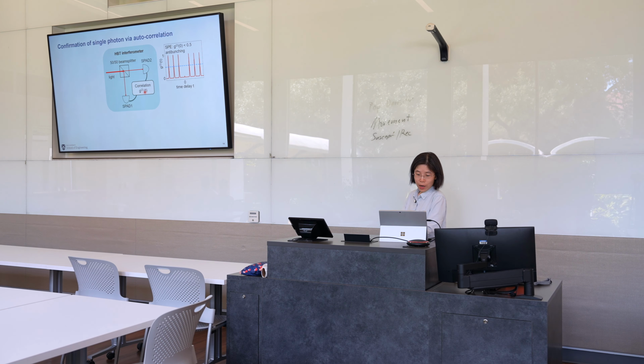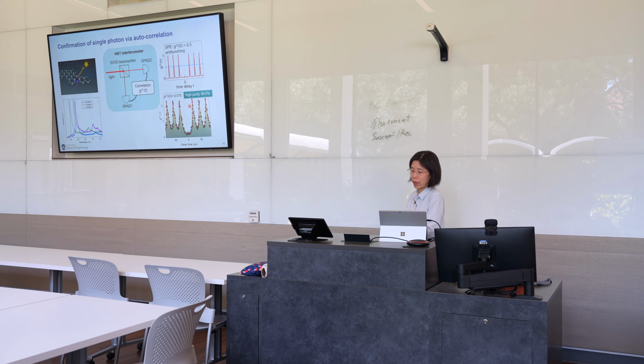Now, if we look at the carbon defects in our boron nitride, we send the emitted light to the HBT interferometer, and this is our experimental result. You can see g2 at zero time delay is very, very small. It is as small as 0.015. And this actually translates into a high single photon purity, 98.5%. The purity is basically 1 minus the g2 at zero time delay. This 98.5% single photon purity is actually one of the highest among single photon emitters in boron nitride at room temperature.